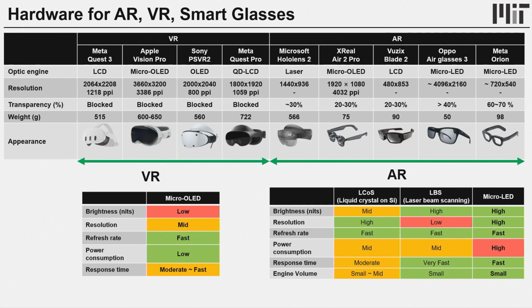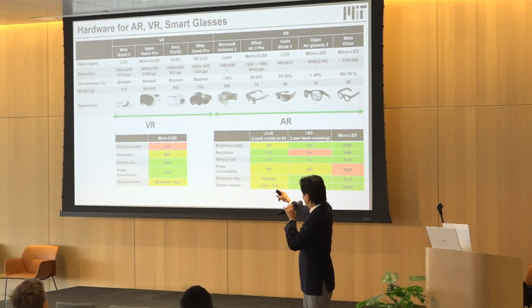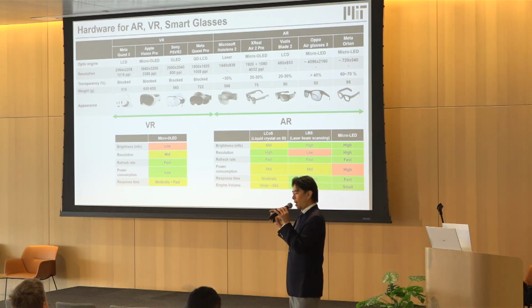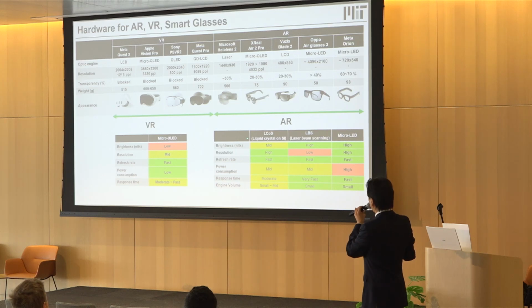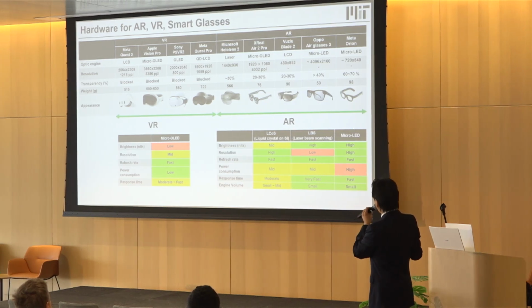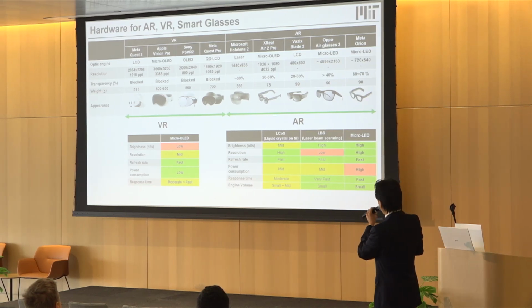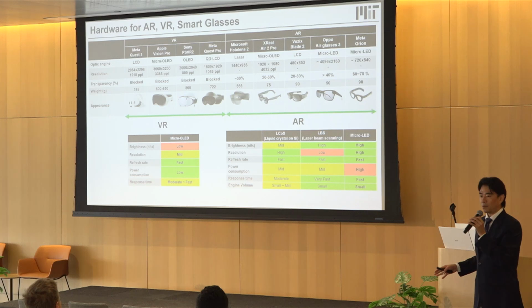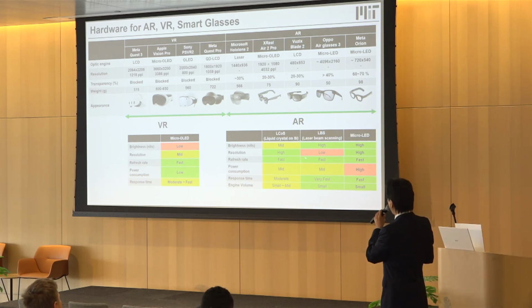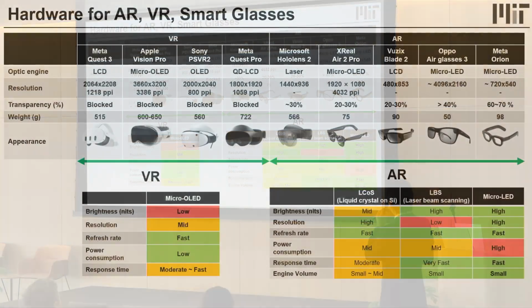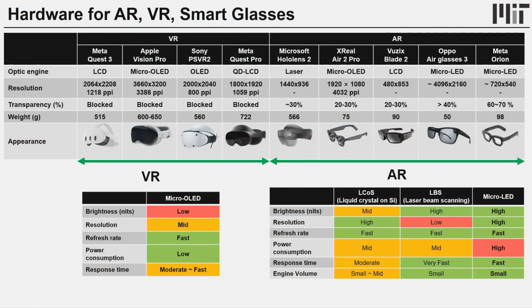My group is more into this sector because, as you can see from this chart, for AR we really have to fight against the sun. If you wear it, you really need to see the display outside. Then maybe OLED may not be the solution, and it has to be something else. But among these three solutions, LCOS, liquid crystal, and laser beam scanning, and micro LEDs, with high brightness, we may have to go in the micro LED direction because compared to these two, micro LED is simply better. But at the moment, power consumption is pretty high, for various reasons that I'm going to talk about.